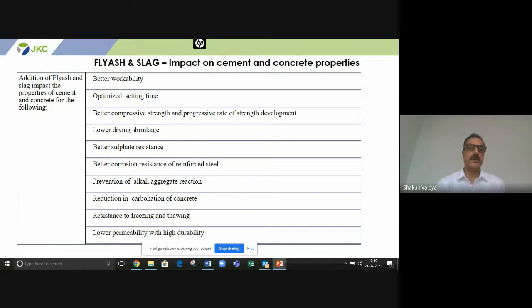It gives better workability, optimized setting, very good compressive strength, lower drying shrinkage, better sulfate resistance for areas like sewage treatment plants or areas which are prone to chemical attacks, and prevention of alkali aggregate reaction, especially in hilly areas where the aggregate is reactive, a reduction in carbonation, resistance to freezing and thawing effect for areas where there are sub-zero temperatures, and lower permeability with high durability. Lower the permeability, higher the durability. This is a thumb rule.